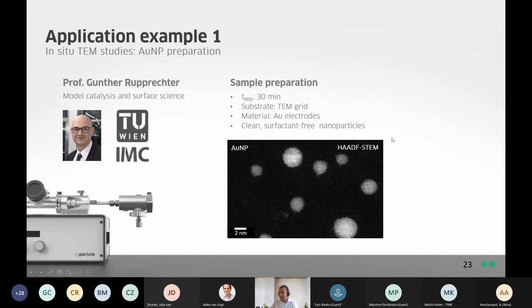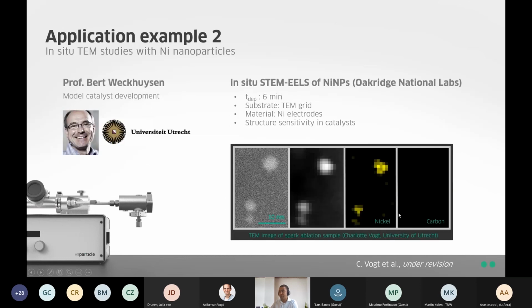Let's say the input material are just gold electrodes, and what you see in the HAADF-STEM image are clean, surfactant-free, and crystalline gold nanoparticles. Similarly, we've worked with Professor Bert Weckhuysen here in the Netherlands. They've been very interested in studying nickel-based catalysts for hydrogenation reactions, and one of his former PhD students, Dr. Charlotte Vogt, used our equipment to prepare nickel nanoparticles on an in situ TEM grid. It took 6 minutes to deposit these nanoparticles onto the chip.